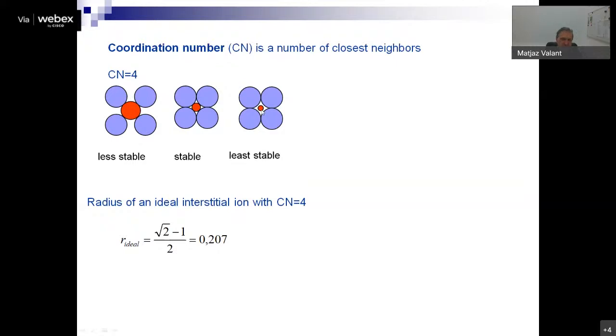In this system, when the red ion is too small, it will have the possibility to rattle around this vacancy, and this will again destabilize the system. So again, we can use simple geometry to calculate what is the ideal radius of this ion to fit perfectly into this vacancy. Well, I can leave this really for your homework. It's so simple. And we can easily calculate that this comes to about 0.2. So such an ion will make a very stable coordination environment, and we can expect then the system to be present in such particular geometry. Now we go to 3 dimensions, of course.